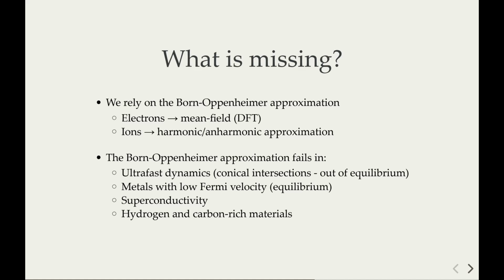But even in equilibrium, for example, if we have a metal with very low Fermi velocity, we know this can violate the Born-Oppenheimer approximation in a significant part of the Brillouin zone, giving non-adiabatic effects. This may be very important in materials with low Fermi velocity, which usually means flat bands, which usually means very high density of states, which usually means very high superconductive critical temperature. So this is very interesting and relevant also for superconductivity.